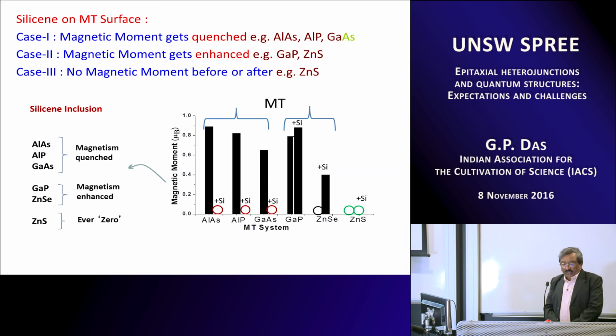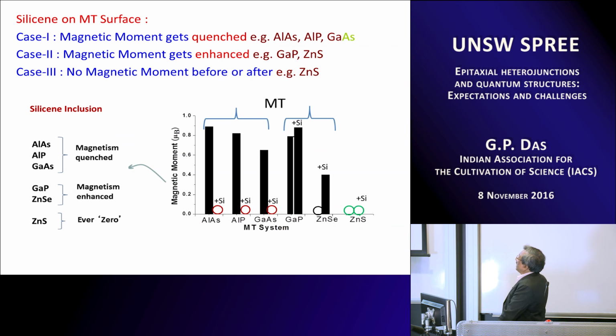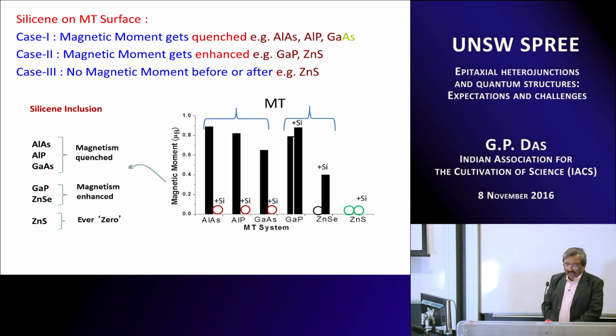Another interesting thing is that there is some magnetic moment which either gets enhanced or quenched depending on what is the substrate. As you can see, for aluminum arsenide, aluminum phosphide, gallium arsenide, etc., when you put silicene on these III-V and II-VI semiconductors, the magnetism gets quenched for aluminum arsenide, aluminum phosphide and gallium arsenide. Whereas for gallium phosphide and zinc selenide, interestingly you can see that the magnetism gets enhanced. Whereas for zinc sulfide, this is neither enhanced nor quenched, it is 0.